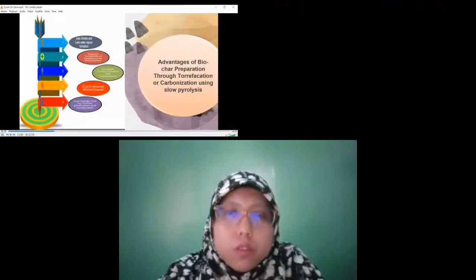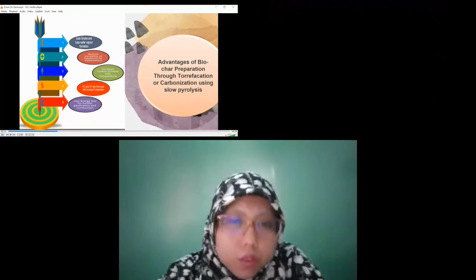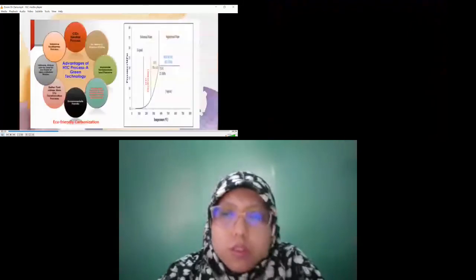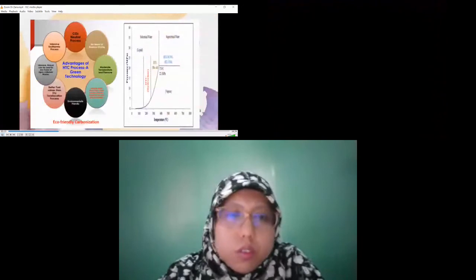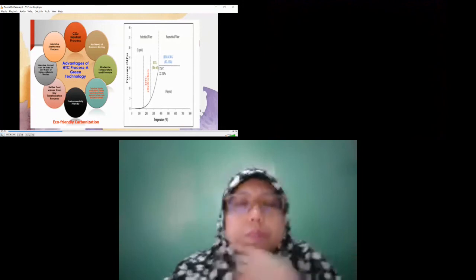We can see that biochar preparation through torrefaction and carbonization using slow pyrolysis has some advantages. It will give less tar inside the activated carbon, and the H/C and O/C ratios will decrease with increase of temperature. That means our carbon proportion will increase. This is hydrothermal carbonization. Sometimes we do it as a preliminary step. Here water acts as a green catalyst, and it will be divided into OH minus and H plus ions at high pressure, and it can disintegrate the biomass substrate into hydrothermal carbon or hydrochar.